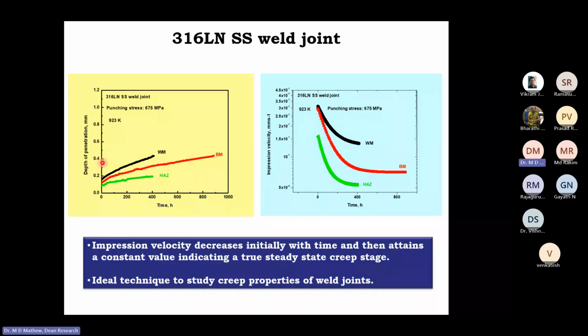Yeah, this is the same data. You process it to obtain the rate. So impression velocity as a function of time. So the creep rate is lowest in the heat affected zone and highest for the weld metal. And the impression velocity decreases with time.